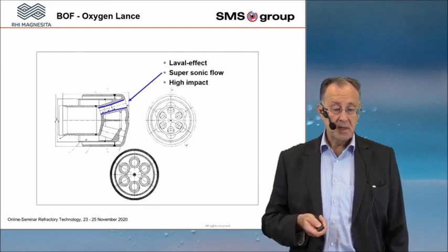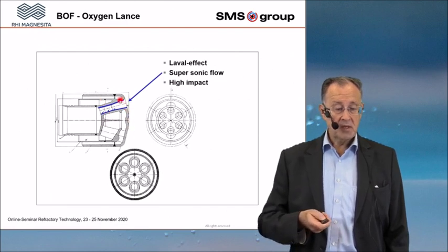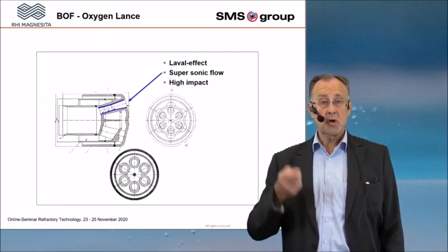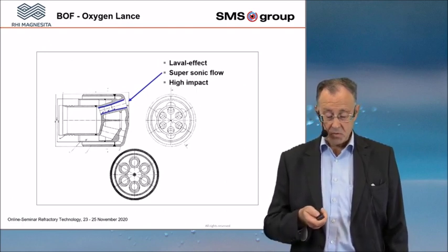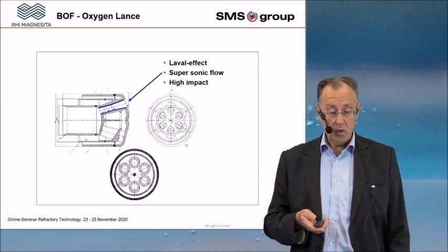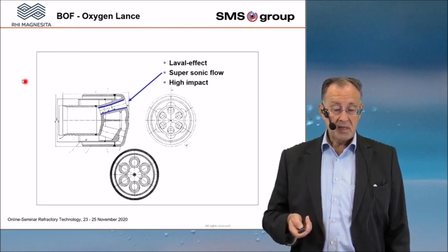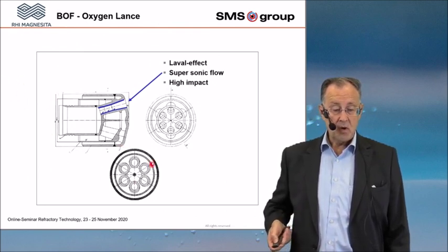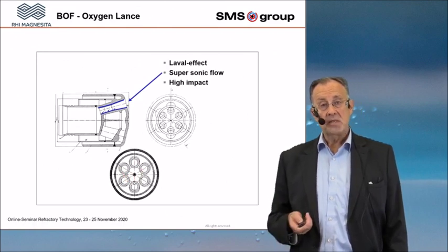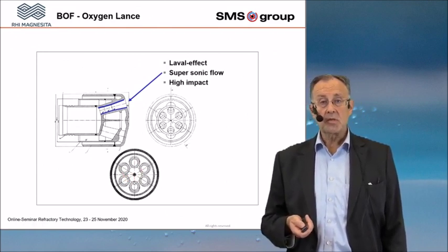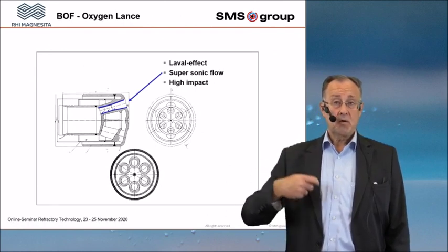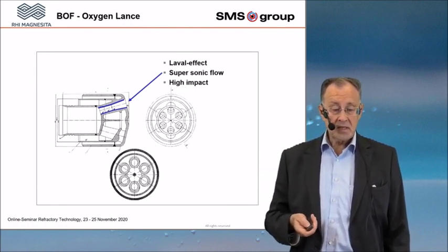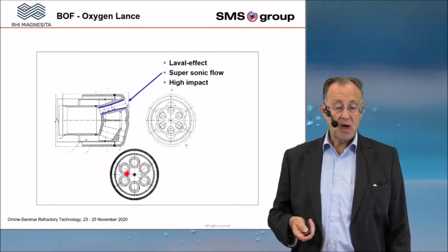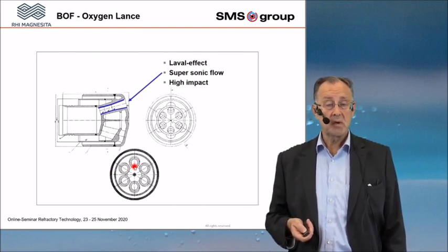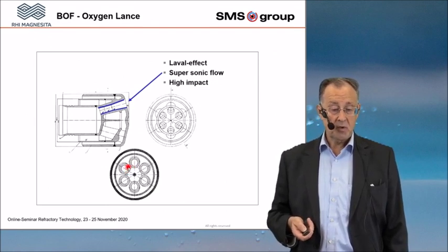of the lance tip. In the inner part you have the water cooling coming in, and then on the outer side, the water is going up to the top of the lance to the water cooling area where you recool the water. Very often the lances have a different number of nozzles, and this depends on the size of the converter, that means the tapping weight and the dimension of the vessel. But in most cases, you have 5-hole lances or 6-hole lances where you blow your oxygen on the surface of the converter.